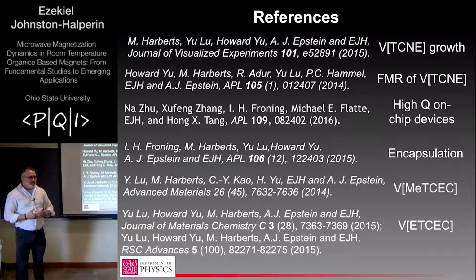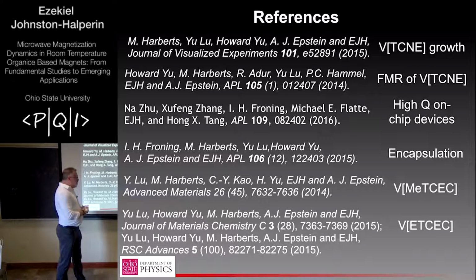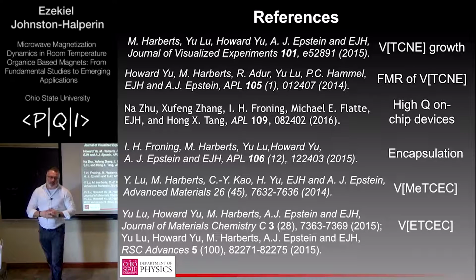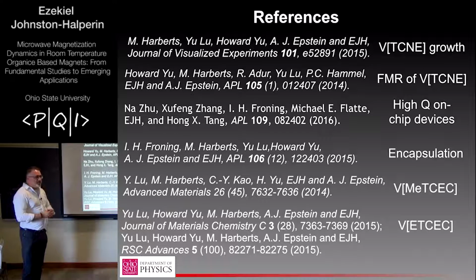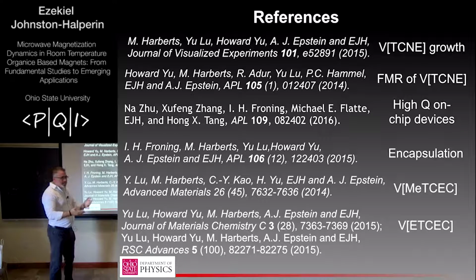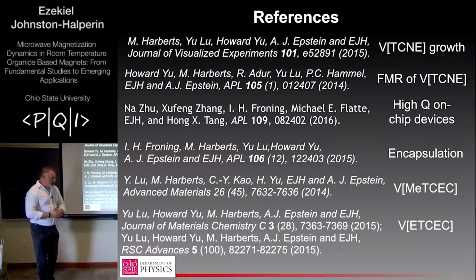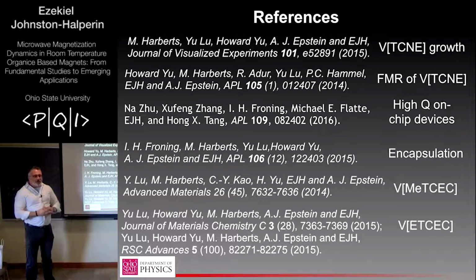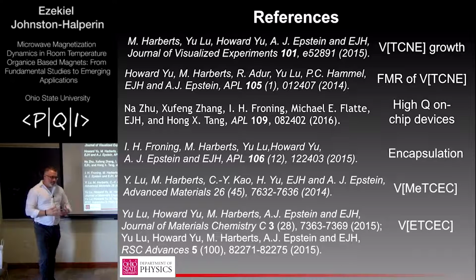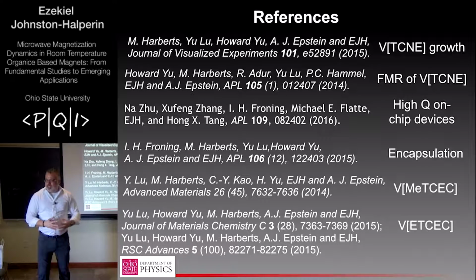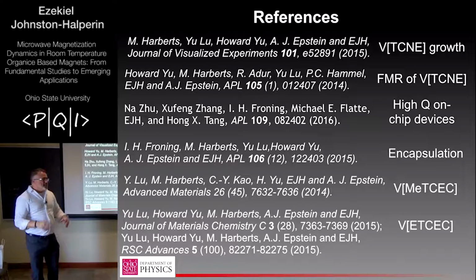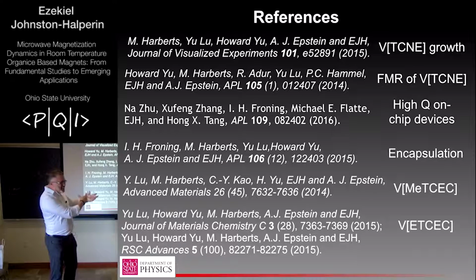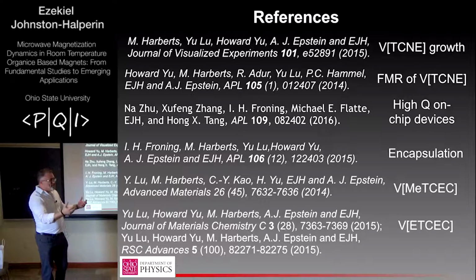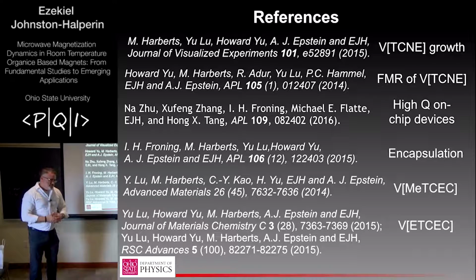Is there any way that you can add more carriers to a system by proximity? Yeah, we've thought pretty hard about that. We've tried a couple of different approaches to doping, co-depositing with other molecules. None of those have really panned out. One of the challenges, as we discovered in this process, is that one person's doping is another person's molecule out-competing your desired precursors for the right bonding arrangement. But we've tried that.